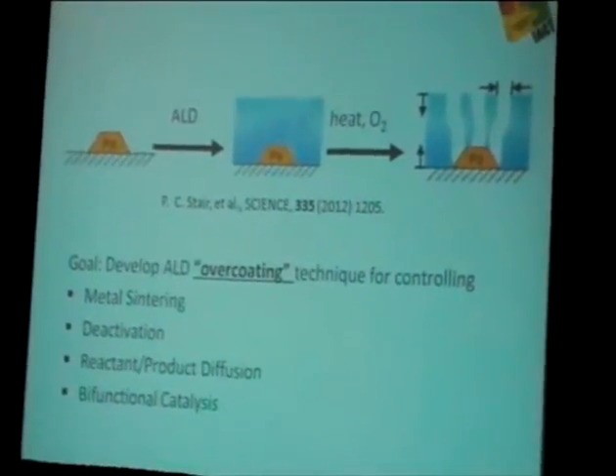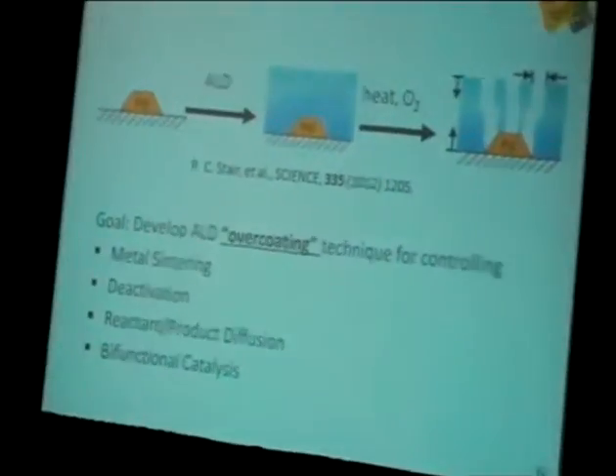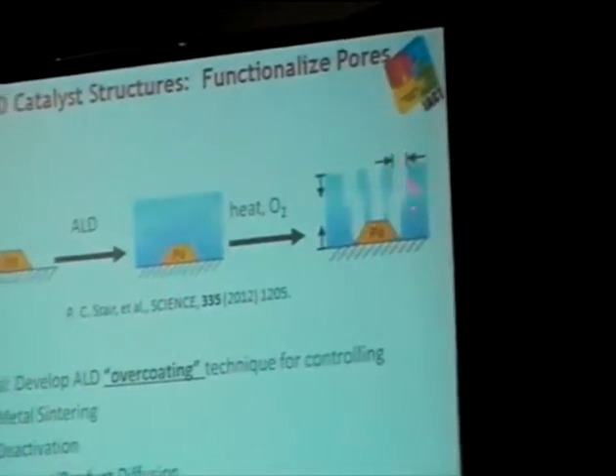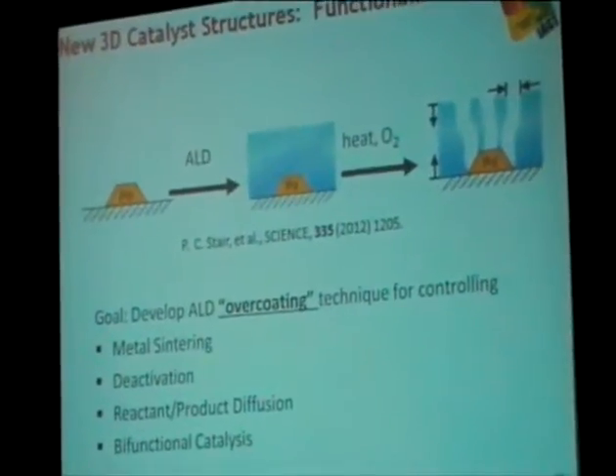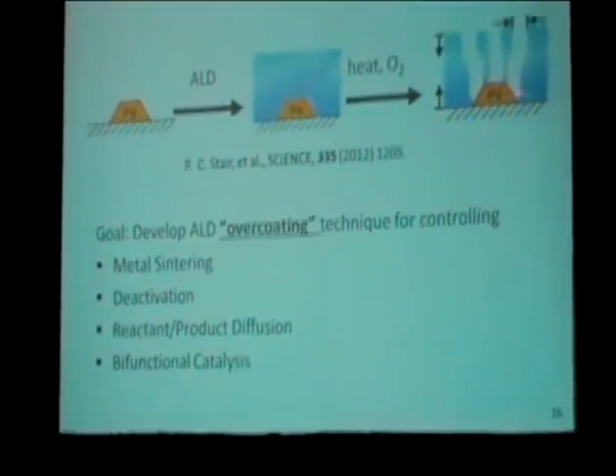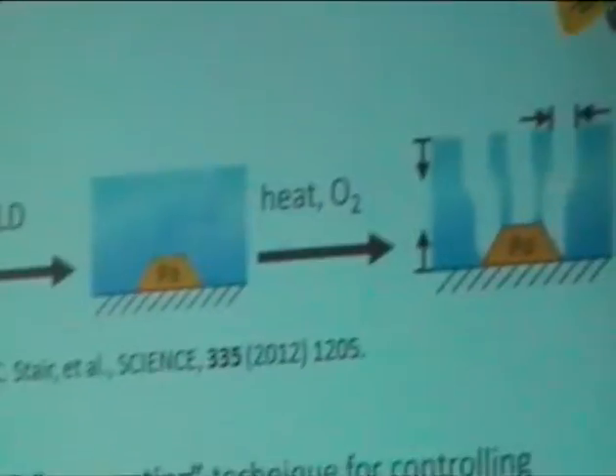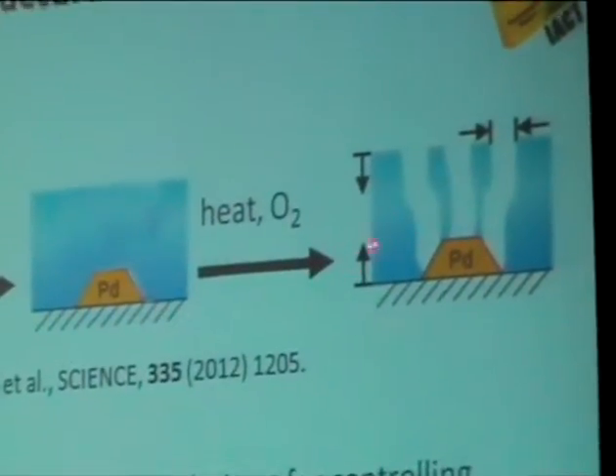They found out that information, but they did one extra experiment in which they heated this material up to 700 degrees in oxygen, and they found, lo and behold, that they actually got some communication back to the palladium surface because of the formation of these cracks, which are on the nanometer size scale. And the nice thing about this specific catalyst is that they found the alumina overlayer goes specifically to the edge and corner sites, preferentially to the face sites, giving rise then to dehydrogenation with very little coking for this catalyst.